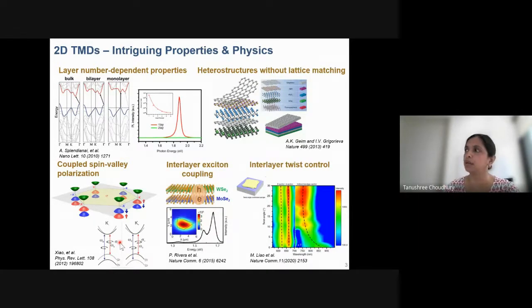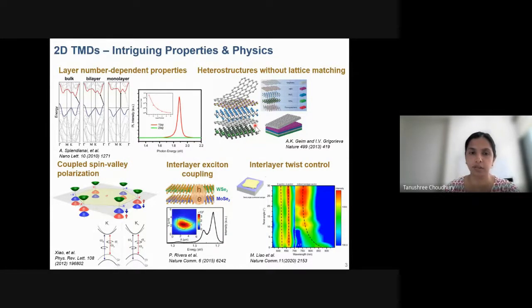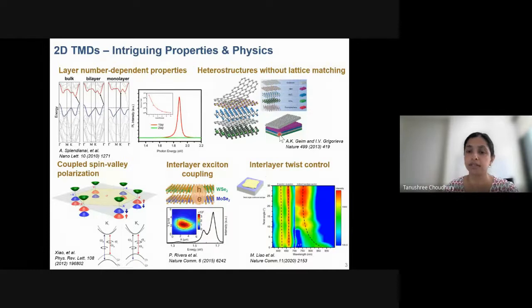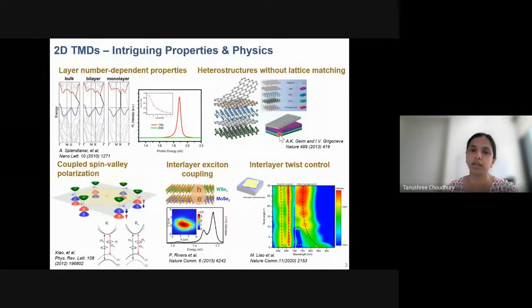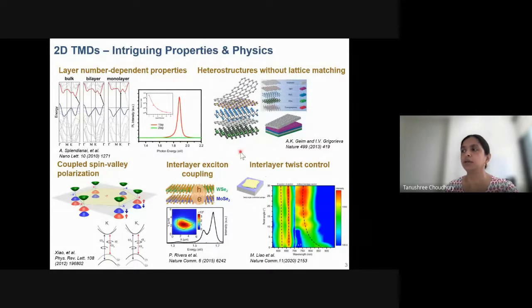The K+ valley couples with right-hand polarized light whereas the K− valley couples with left-hand polarized light. In addition, given the transition metals present in these materials, there is also spin-orbit coupling which splits the valence band. This allows you to create charges of a particular spin, creating a situation where both spin and valley are coupled together — you can use one to produce a spin of a particular kind. These materials can be combined into heterostructures without taking into account lattice matching, treating them like Legos placed on top of each other for an all-2D electronic device.